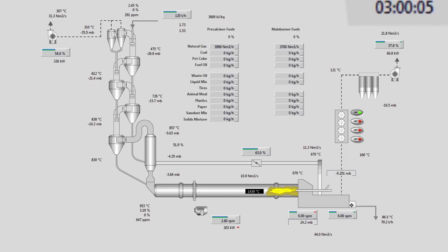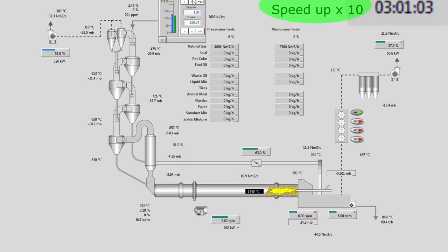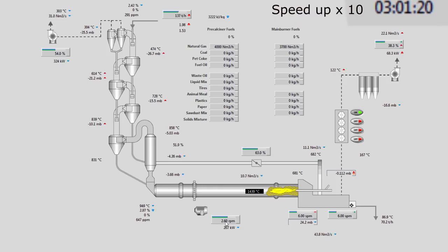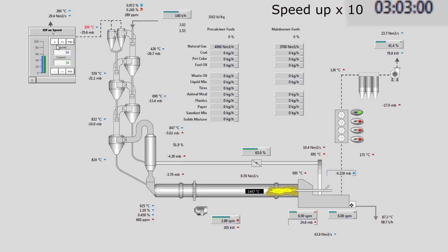3 hours, 120 tons per hour, 2.6 RPMs kiln speed, 51.9 precalciner fuel. Let us speed up the system to quickly see what will happen next. Increasing all the settings, evidently too fast, reducing CO2 drastically and generating CO.